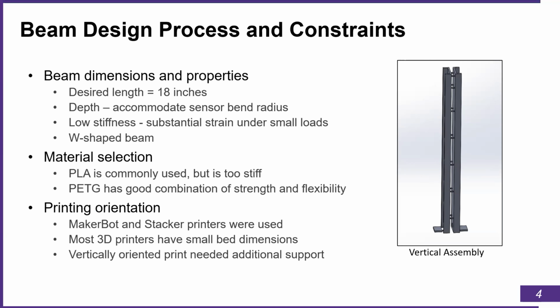So with the material selection, we chose PETG material. PLA is very commonly used, and it's good for most applications. But for our project, it would probably be too stiff. So we decided that PETG was going to have a good combination of strength and flexibility to get that strain, like I previously said. And then we used MakerBot and Stacker printers. We had one vertical print and one horizontal print. The MakerBot we use vertically, and the Stacker we use horizontally.